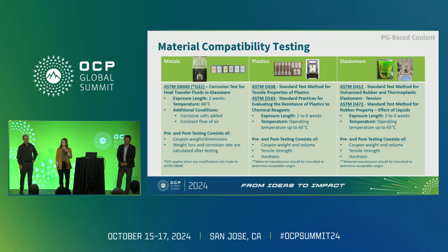For plastics and elastomers, there's two more tests. ASTM D638 and 543, and then D412 and D471. Those are exposure tests where you would immerse coupons of the plastic or elastomer in the heat transfer fluid, exposed for 2 to 6 weeks at your usage temperature, or slightly higher if you wanted to do a worst case scenario. Before and after testing, you would weigh the materials. You would do volume measurements, tensile strength, hardness, and then calculate the change over the exposure length, and determine if the material is suitable for use.